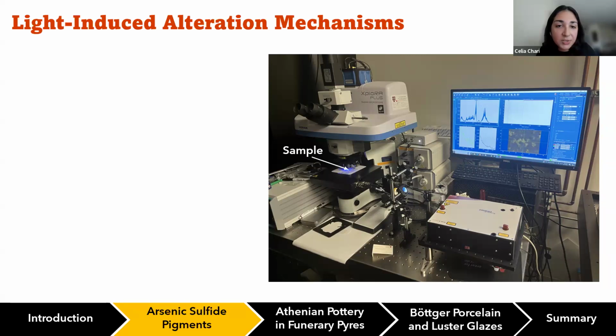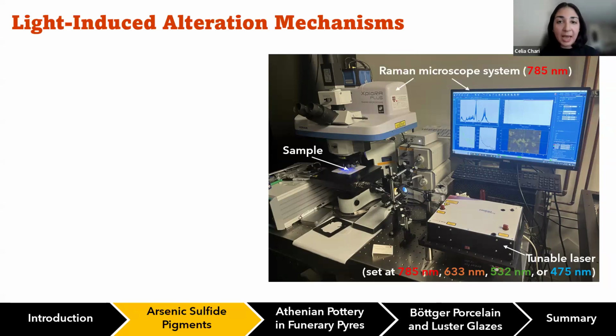In a nutshell, we have our sample on the stage of the Raman microscope. We have a laser that is pointing directly at the sample, and these are tuned to different wavelengths. And this is to better understand whether it's specifically red light, amber light, green light, or blue light that is triggering this photochemical reaction. And then we have a Raman microscope system that is just collecting data using a 785 nanometer laser. And that these spectra are being taken every 2 seconds. So we have a clear understanding of how the structure is changing with time upon these exposures to light.